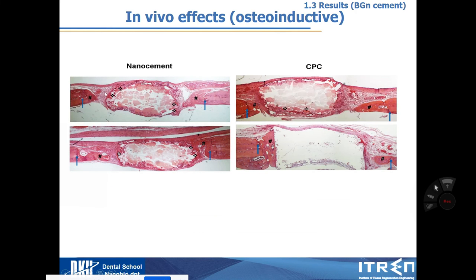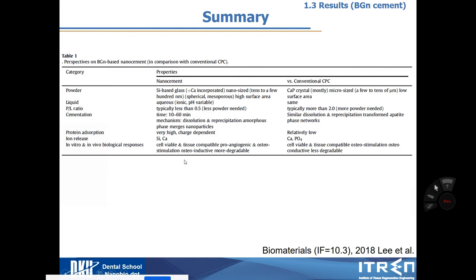So we also check the other rat calvaria, same as before, osteoinductive, osteoconductive. You can look at the asterisk. And then this is some summary of nanocement and conventional CPC. So we can say that nanocement has very good ability to regenerate bone compared to commercially available material. But the only drawback is they have very poor mechanical properties. This is the thing we have to overcome later.